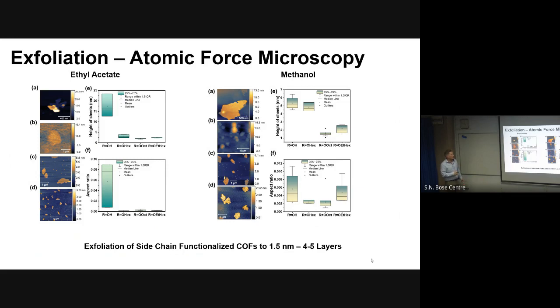Very interestingly, we did some statistical analysis of roughly 10 to 20 sheets. Here we have the interquartile range, so 50% of the sheets lie in this size regime. What we can see is that if we have the hydroxyl groups, the sheets are much thicker in the case of ethyl acetate and methanol. If we have the octyl side chains, we can get very, very thin sheets. If we exfoliate them from methanol, they are at roughly 1.5 nanometers, which corresponds to 4-5 layers. One thing that also happens during the sonication treatment is that we don't only make the sheets thinner, we also break them along the layers, which is an unavoidable problem, I think, because we need to put in the energy, and the sheets will break along the layers.